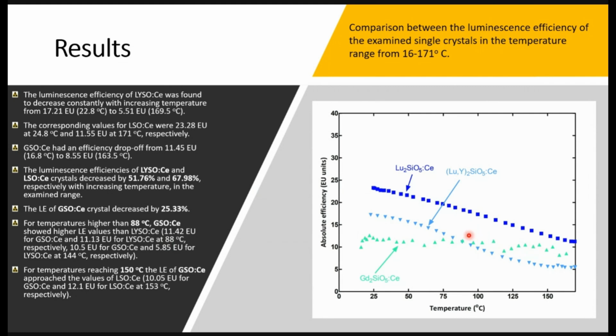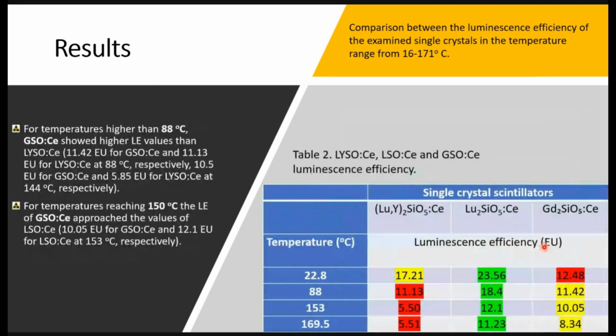Also, we can see that after about 88 degrees, the signal produced by the gadolinium detector is higher than the lutetium-yttrium detector, which is much higher and has a higher light yield in lower temperatures. At even higher temperatures, the signal of the gadolinium detector approaches the signal from the pure lutetium detector. This is also an interesting finding.